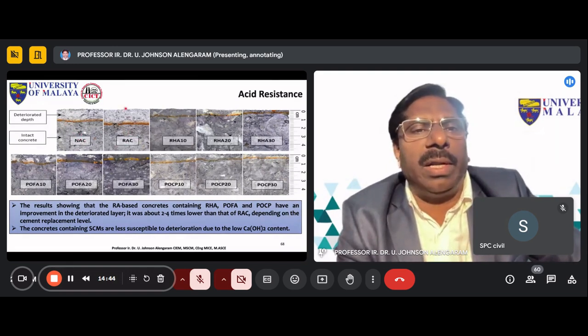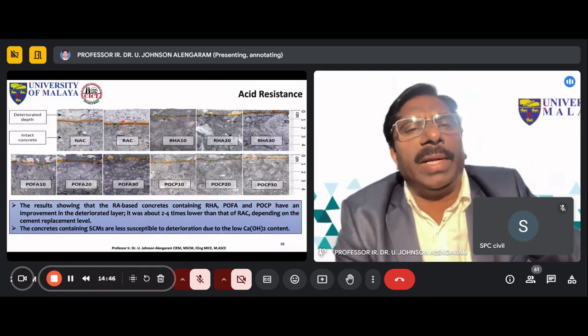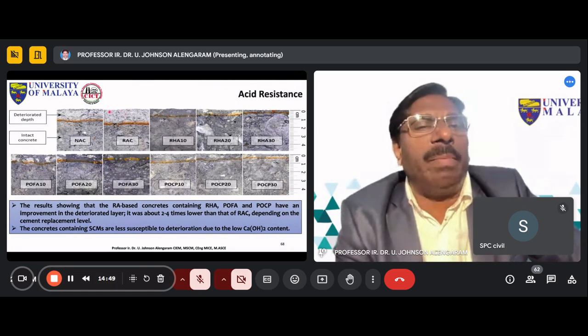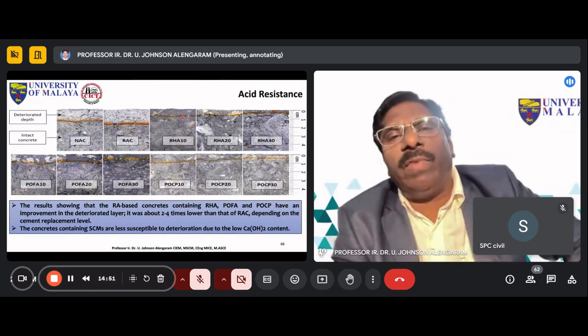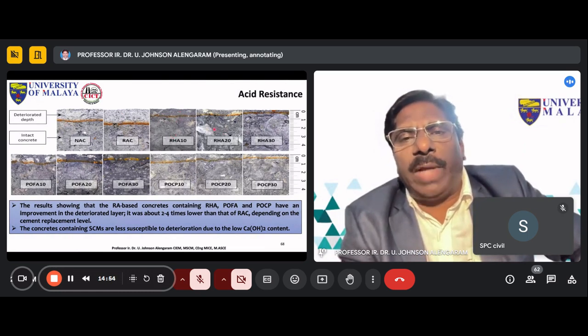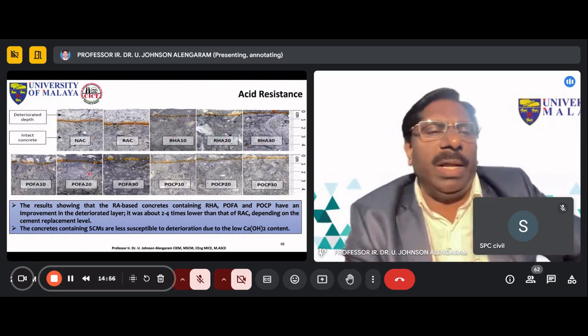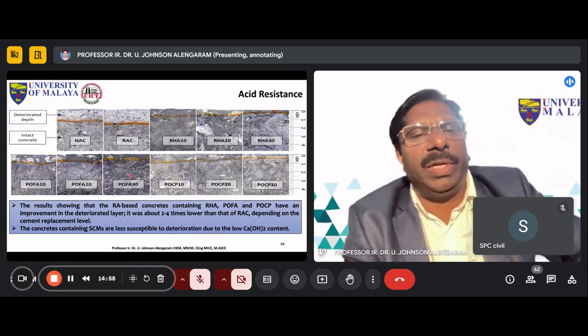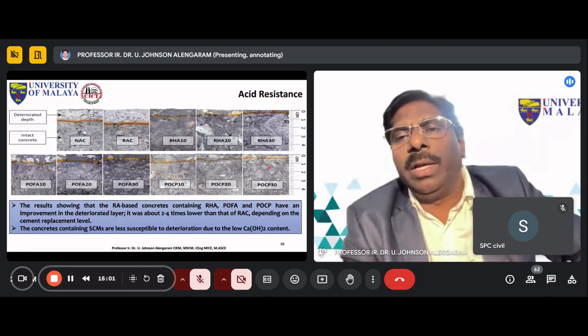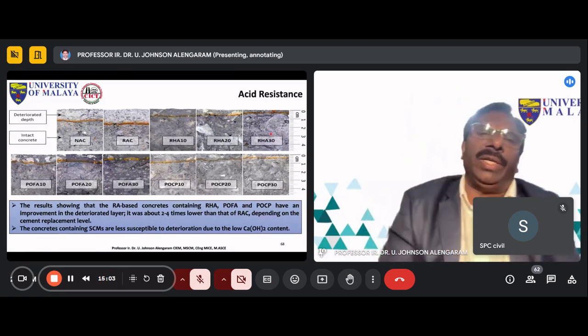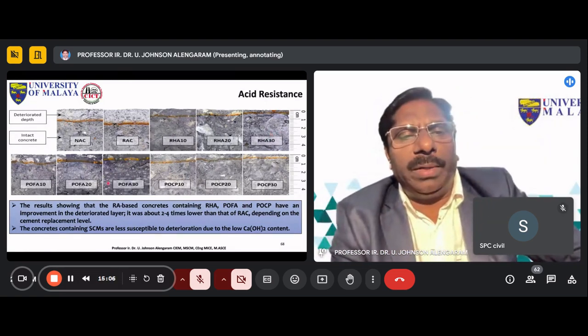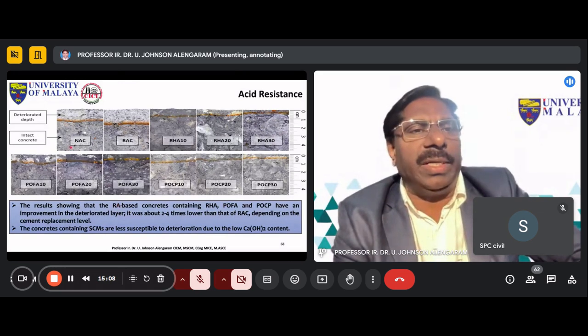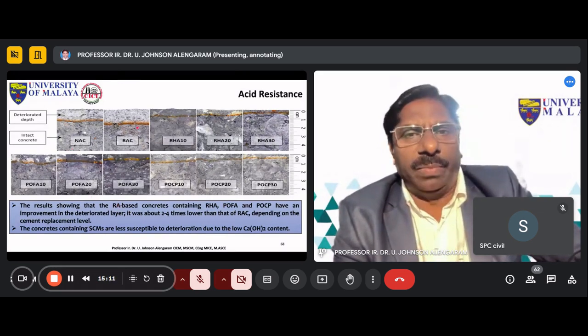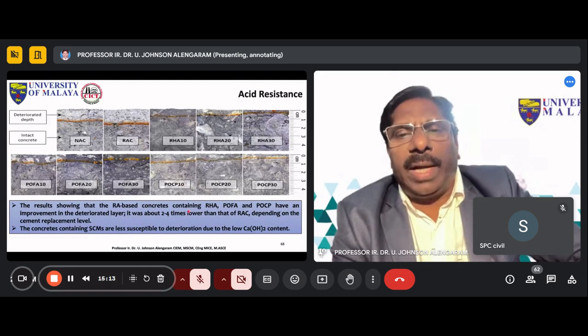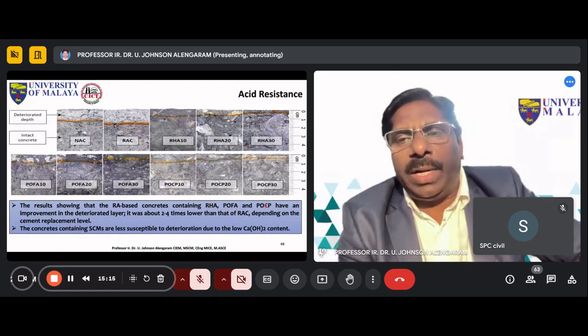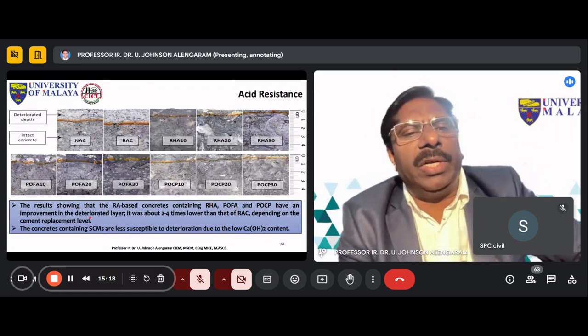this is a recycled aggregate concrete. We expected recycled aggregate concrete to have more deterioration compared to the normal aggregate concrete. However, when we add rice husk ash of 10%, 20%, 30%, similarly palm oil fuel ash 10%, 20%, 30%, same with the palm oil clinker powder, you can see the reduction in the deterioration of the surface. So the results show that recycled aggregate based concrete containing rice husk ash, palm oil fuel ash, and clinker powder have an improvement in the deteriorated layer.